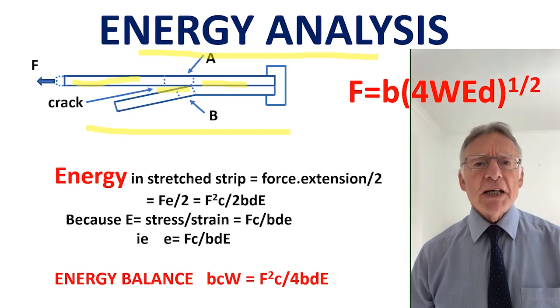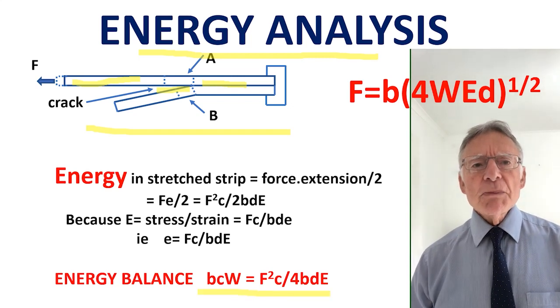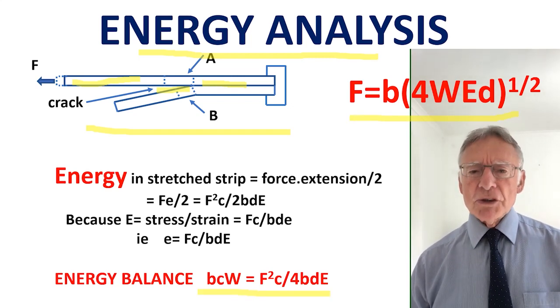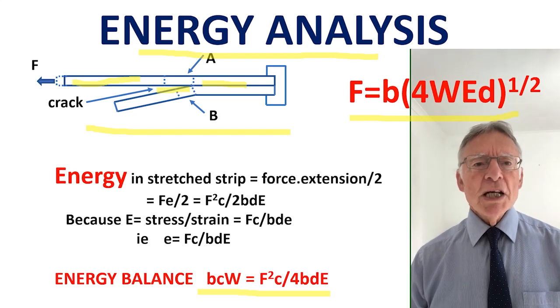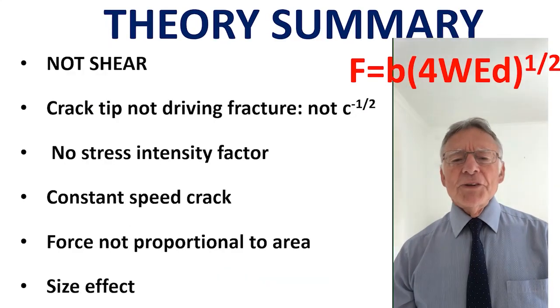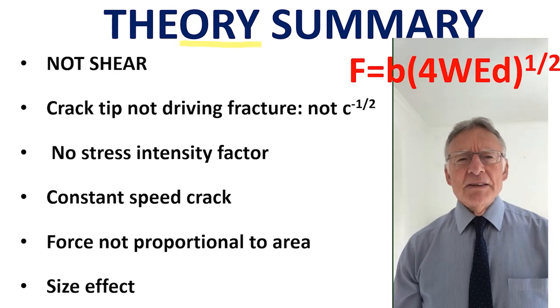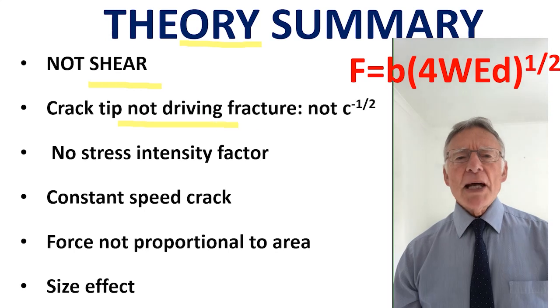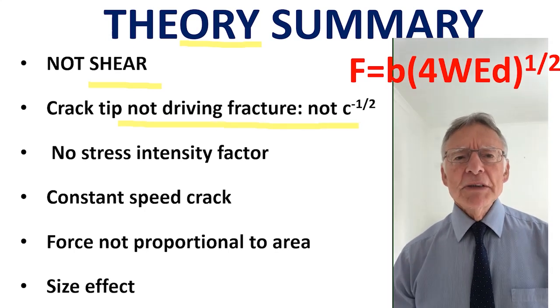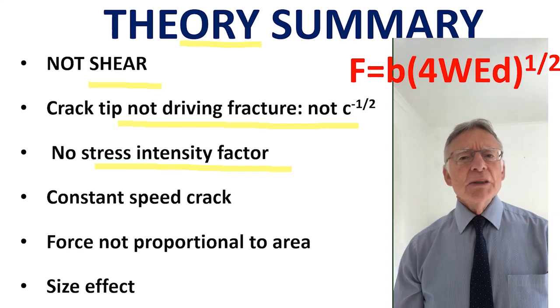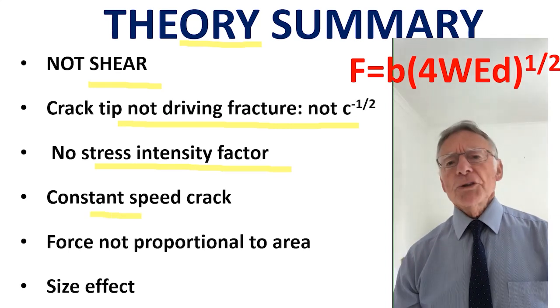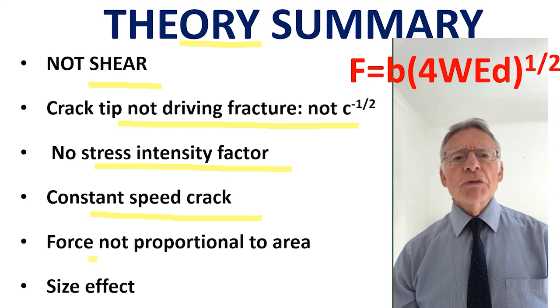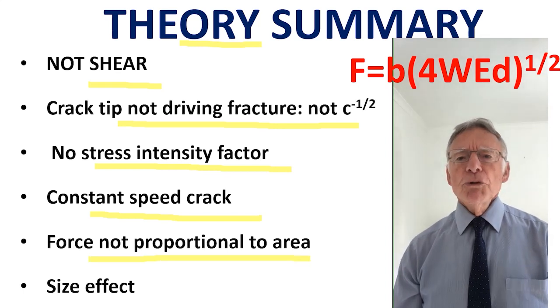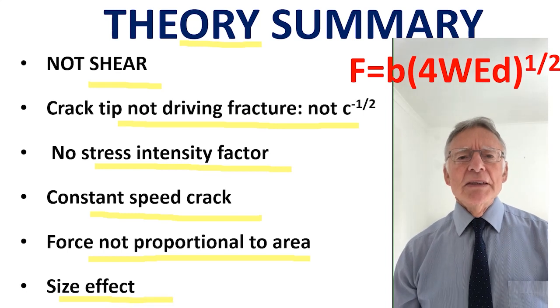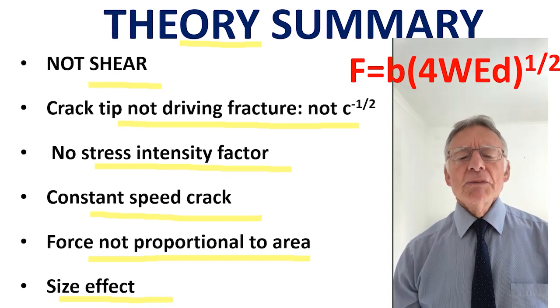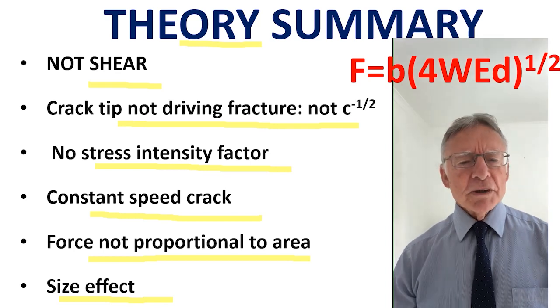There is no stress intensity factor. The Griffith argument leads to this simple result, and the equation has the same dimensions as the Griffith equation, but completely different behaviour. The theory shows that it's not shear. Also, the crack tip does not drive the crack. It's not c to the minus a half. You may find it surprising: there is no stress intensity factor. The crack goes at constant speed, unlike the famous Griffith crack, which accelerates. Moreover, the force is not proportional to the joint area. The joint gets weaker as you scale up. So strength can be any number you want.